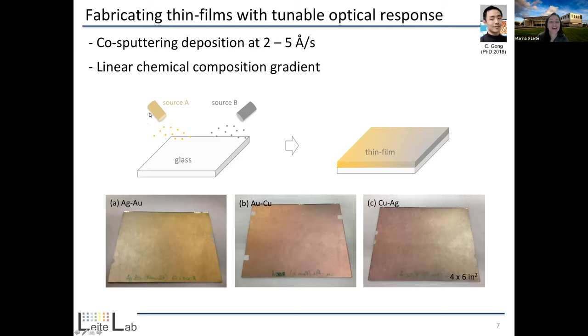So essentially, we do co-sputtering deposition of two metals in this particular case. And we do that by controlling very carefully the chemical composition gradient that we have within one of those glass substrates. And I apologize here for the lack of scale. These are glass substrates, they actually are 4 inch by 6 inch. So they're quite large, literally.